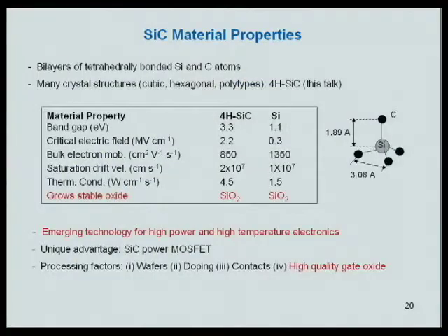The thermal conductivity of silicon carbide is higher, which is important for removing heat from circuits. But the key feature that makes silicon carbide interesting for MOSFET applications is that both of them have this stable oxide, SiO2, which is not true of the other compound semiconductor wide bandgap materials. So silicon carbide can be used for technologies where we want to operate the devices at high temperatures, because the larger bandgap helps with that, and at high power, because the larger breakdown voltage helps as well.